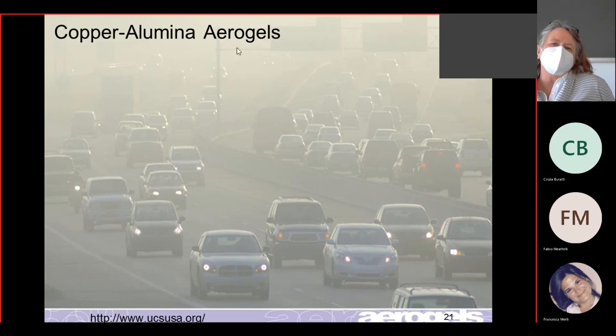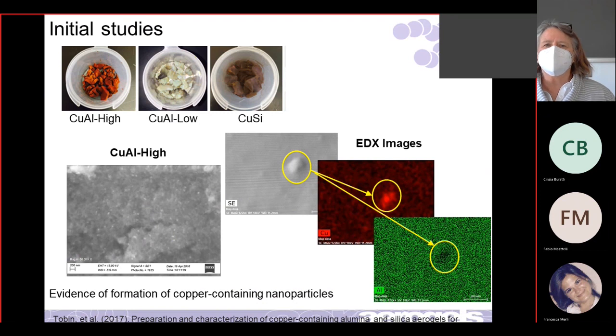So these were some initial studies we did, and one of the problems when you have the wet gel and you put it in a solution containing copper, you don't know how much copper goes into the gel. So we looked at an experiment with what we called high and low. We put a lot of copper. You know, the ethanol in one case had a lot of copper, in the other case less copper. So we called it high-low. And we did it with alumina, and we did it with silica.